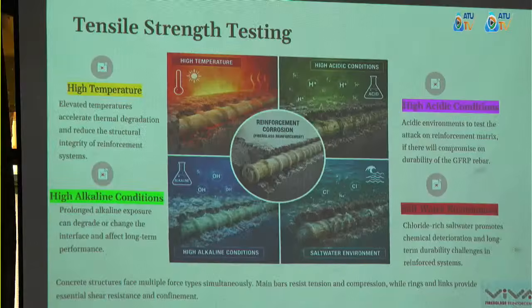I was able to concentrate a 0.1 molar sulfuric acid, achieving a pH of, I believe, 1.54. So very concentrated acid. I subjected the sample for 7 and 28 days to test for early stage corrosion and late stage corrosion. Then I moved on to high alkaline conditions, because we know the concrete is very highly alkaline. So I subjected it to concentrated calcium hydroxide, because the material properties could change once the fiberglass is submerged inside the concrete. So I did it as well for 7 and 28 days for the early stage curing and the late stage curing.